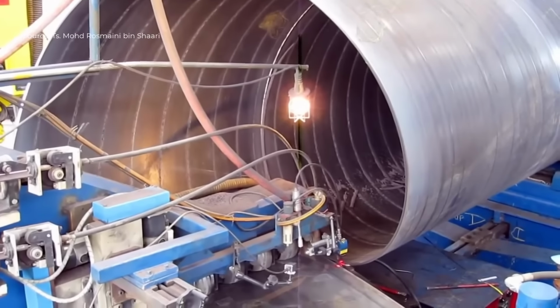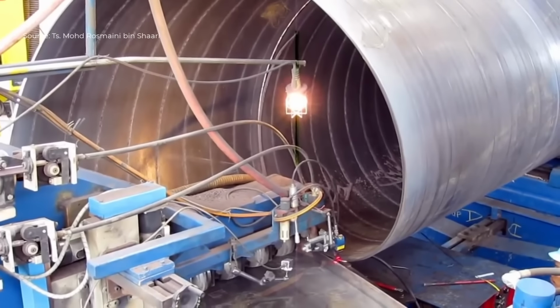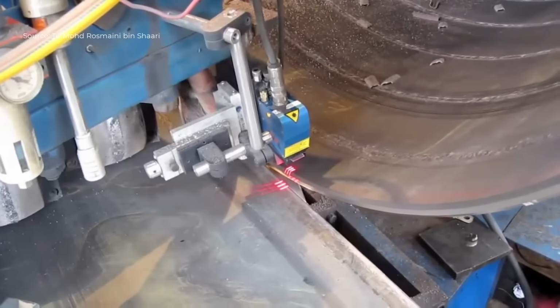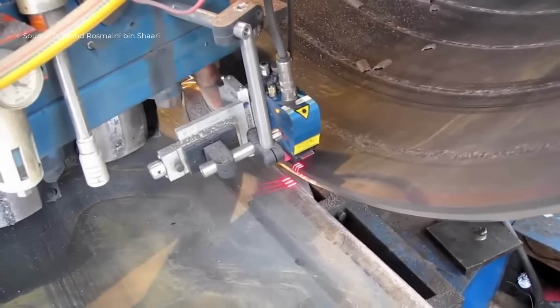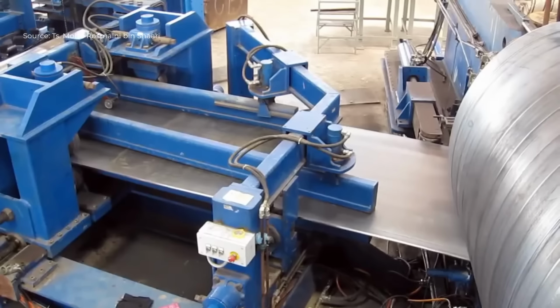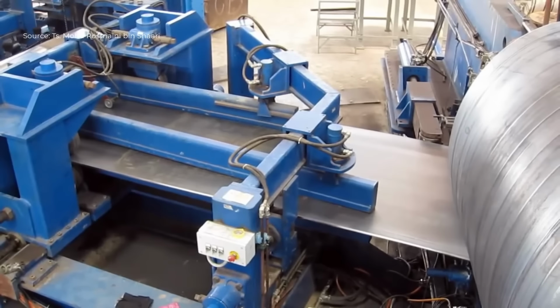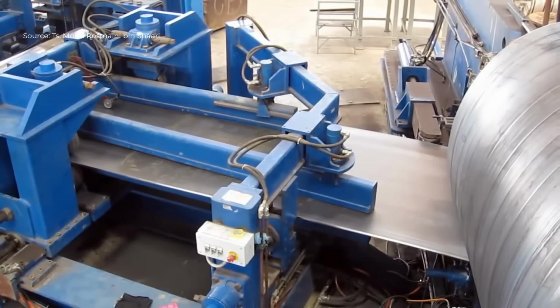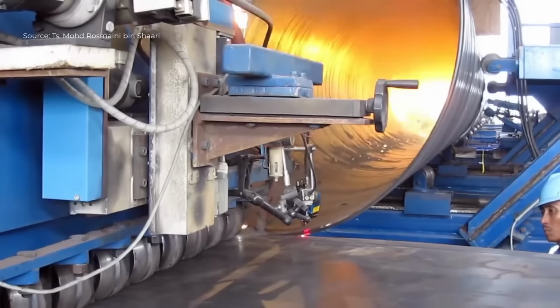the arc. The internal SAW process reinforces the joint by fully penetrating the seam from the inside, ensuring complete fusion through the pipe wall thickness. This step significantly increases the mechanical strength of the weld and eliminates any potential internal defects left after external welding.